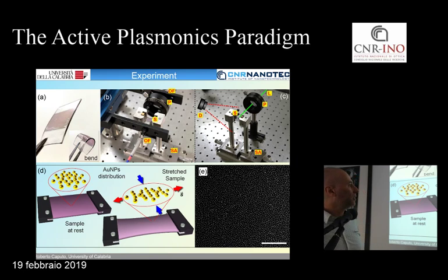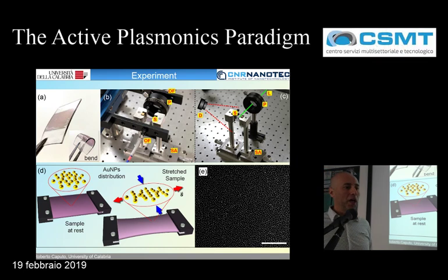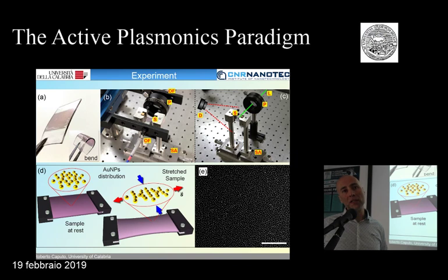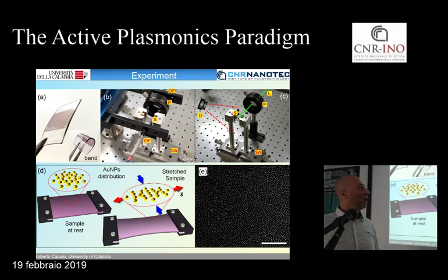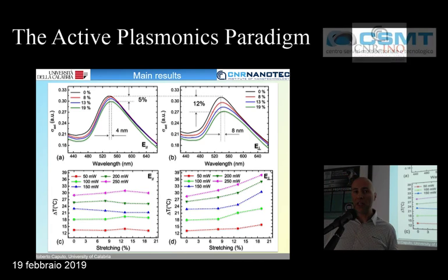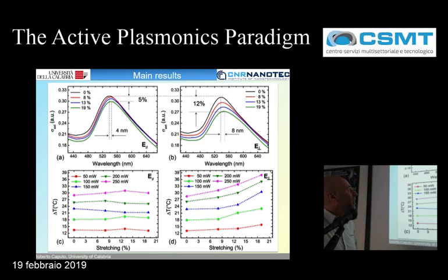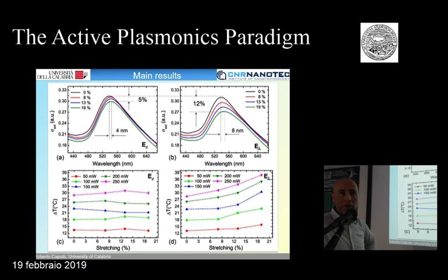So the idea is that you can perform an extinction experiment while pumping your sample. And we can see as an experimental result the change in the extinction cross-section of the sample by applying different pump intensities. So these are the real results. You can see some similarities with the previous experiments where we just monitored the position of the plasmonic resonance.